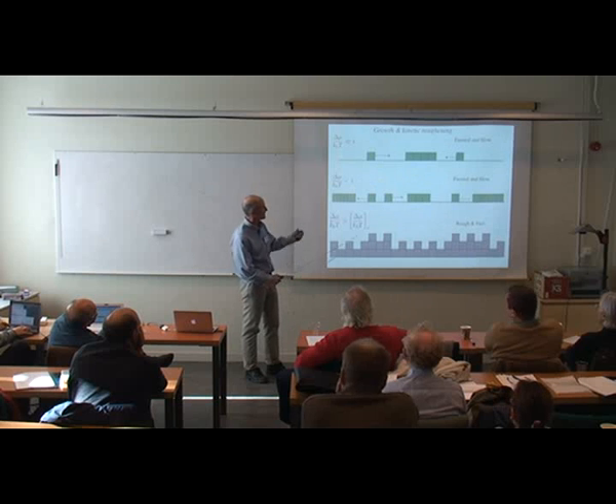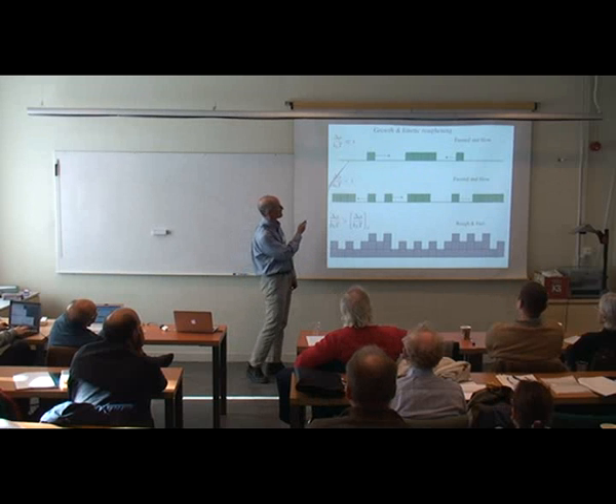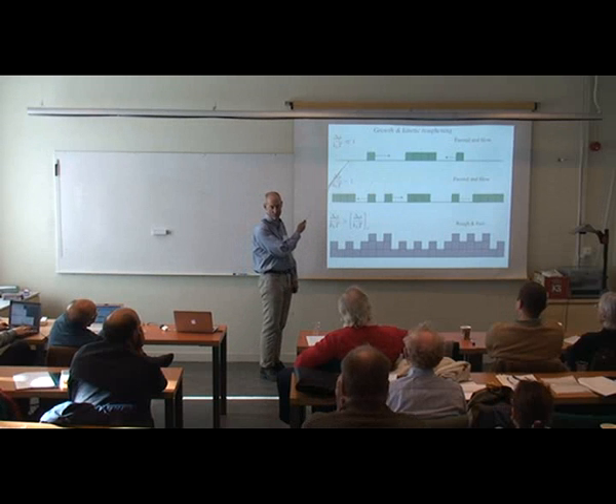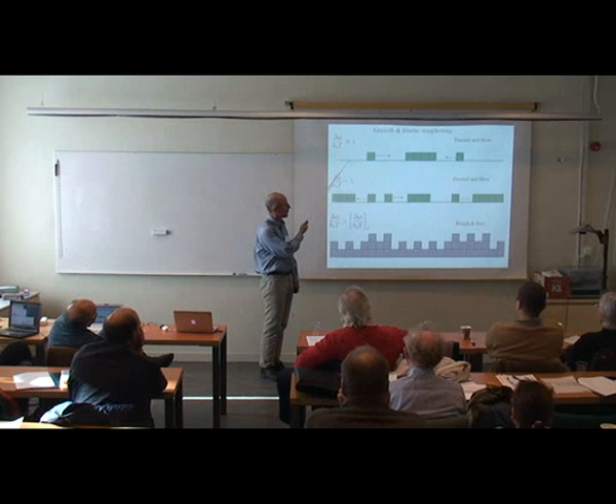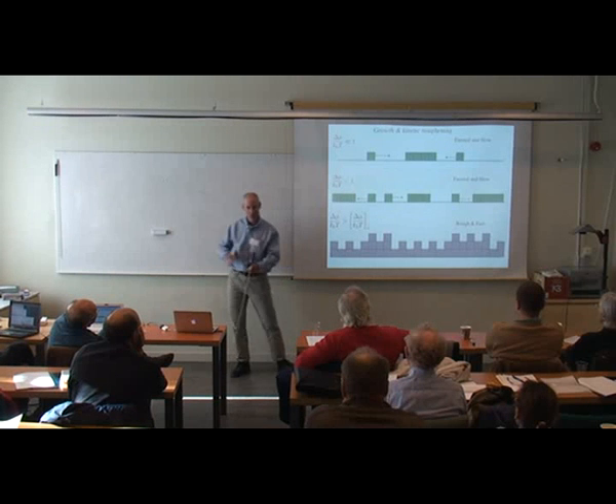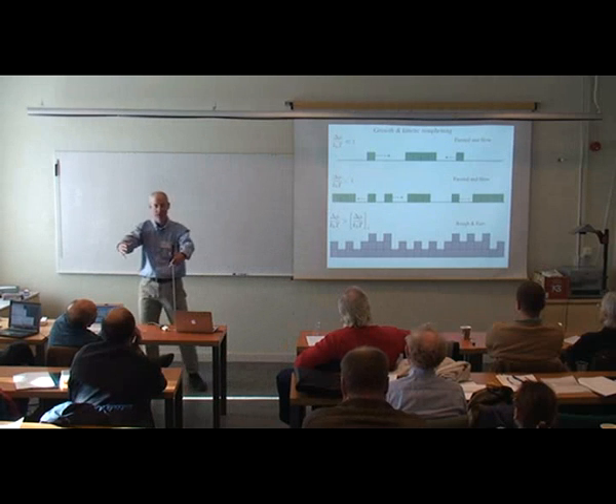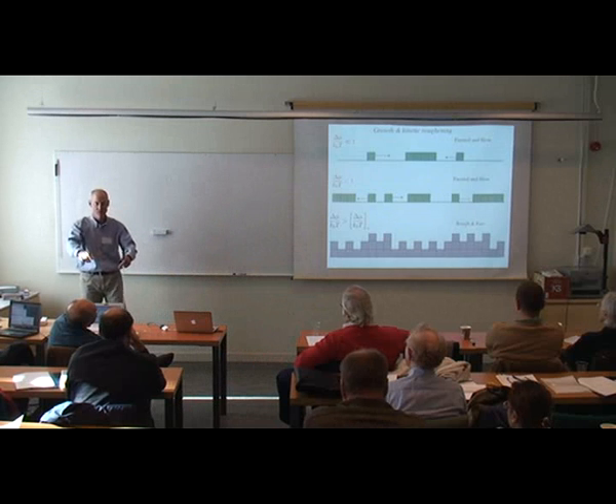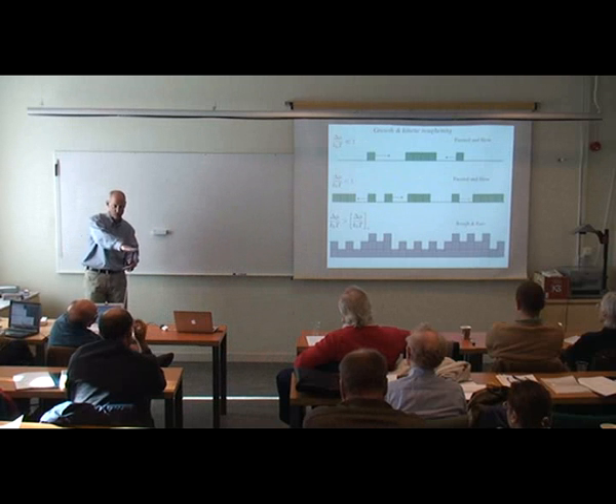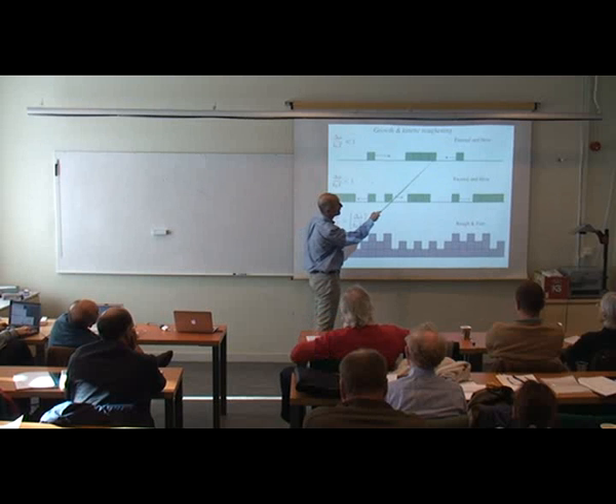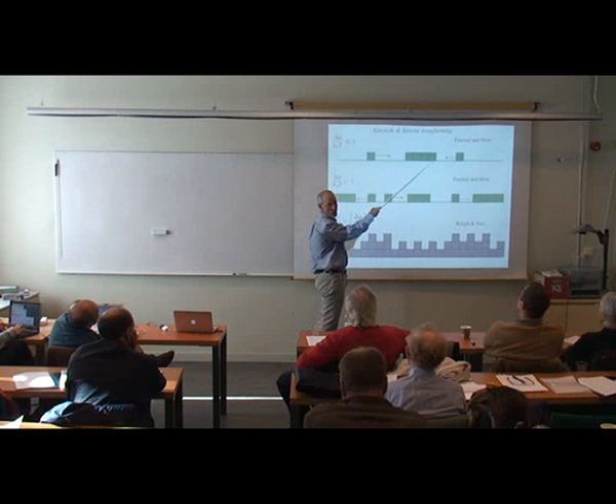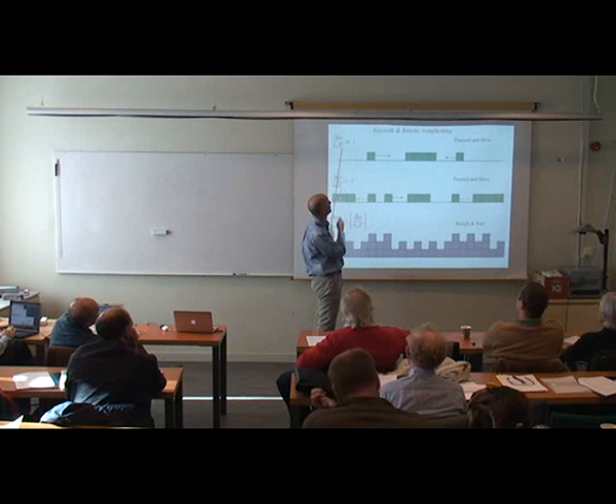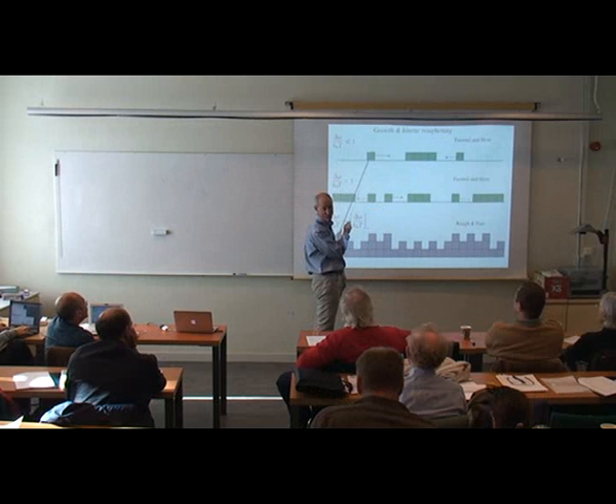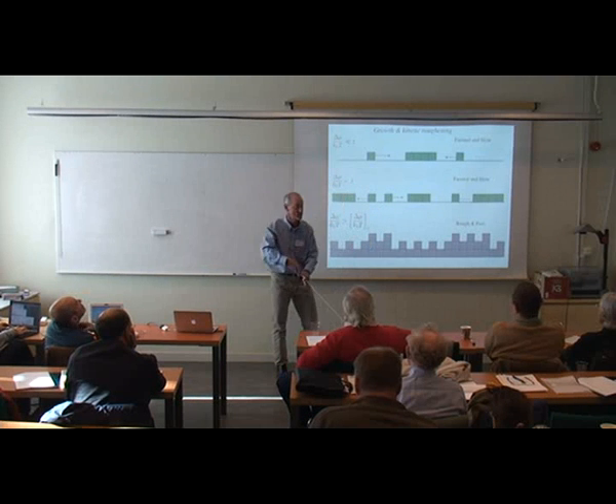Right. Disequilibrium transitions. Imagine I have a facet and I want to grow it normal to itself. Okay? Well, one atom doesn't do the job. I have to get a bunch. So I have a nucleation problem in lower dimensions. So I have a line-to-surface barrier to creating this two-dimensional nucleus on the surface. And it suggests an interesting problem of arrested equilibrium. That is, I can have a finite delta mu but a non-moving surface, right? Because I can't overcome the nucleation barrier of this pillbox on the surface.